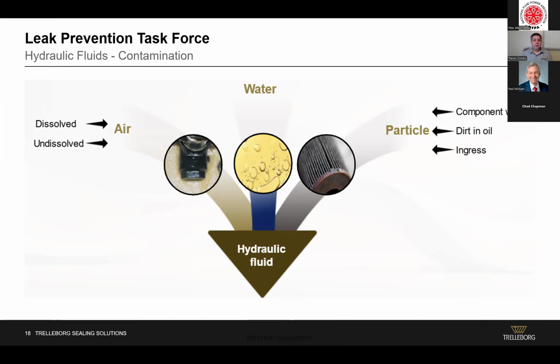It also is important to note here that the contamination can come from internal sources as well. So we see that quite a bit where there's component wear in the system, and that's creating particles that then get embedded into the seals and can cause additional damage, either to the hardware or to the seals, to the rod, creating scratches, and those can eventually become leak paths. So contamination is an important factor to keep in mind. And I think it's important to understand where that contamination comes from, where that source is, so you can eliminate that source.